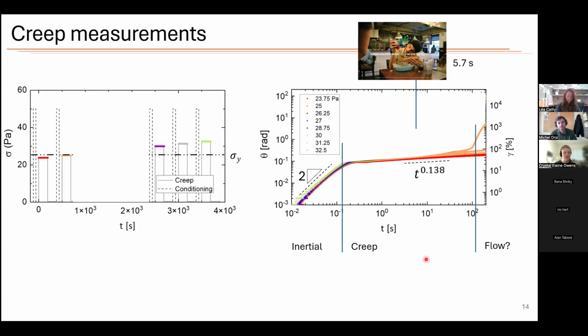Now, if we apply higher level stresses, so these are stresses that are well above the yield stress, then we get flow. And so here, as the stress increases, you see a definite transition from material that acts relatively like a solid to fluid that is flowing readily. And this has a slope of 1 up at the top here. That is just basically pure displacement. There's no inertia, it's just material flow.